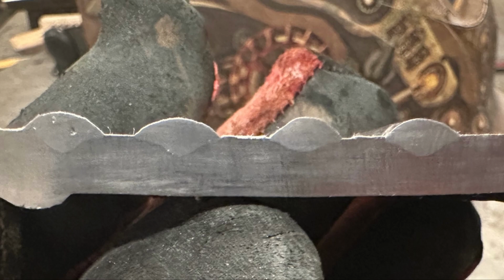You can see down at the root of the joint where the penetration's the deepest, that little white speck is porosity, and we'll see it on the other side of the plate as well that I cut and etched. Now the third and fourth pass, which I ran gas with, seemed to have less penetration than the first two. That's not what I really expected, and I cut and etched the other side of the plate as well just to get a better idea if it's just this particular area of the plate or if it's both of them.